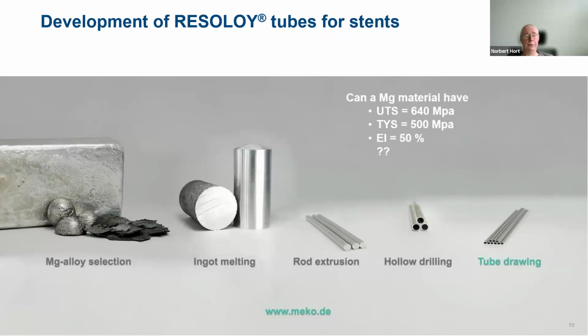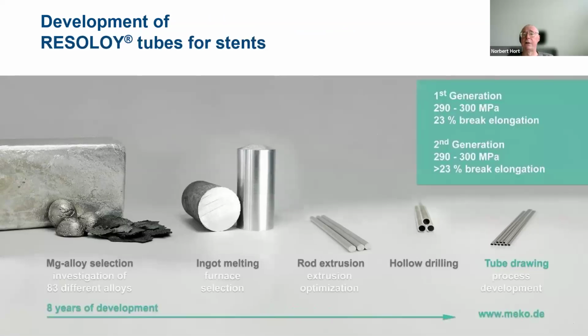And what is also the question when we started the discussion more than 15 years ago, we found that we don't need 640 megapascals. We don't need 500 megapascals yield strength, and we don't need 50% elongation to fracture. Basically, these values were derived from steel, but finally we found out that something in the area of 300 megapascals tensile strength is okay. Then a bit more than 20% elongation to fracture is also okay.